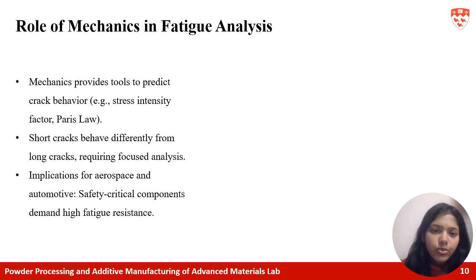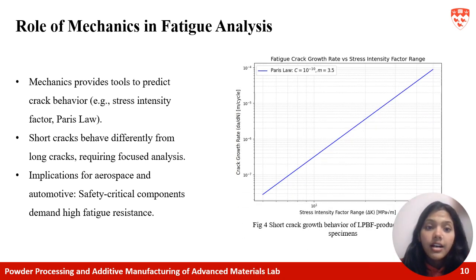So here the crack growth rate depends on the stress intensity factor delta K. When defects are present, they act as stress concentrators, increasing the delta K locally and accelerating the failure. In simpler terms, defects are like weak links in a chain, and they dictate where and how fast the fatigue is going to occur. So this graph demonstrates the relationship between crack growth rate, which is dA/dN, and the stress intensity factor range, delta K, highlighting higher growth rates due to residual stresses and process-induced defects.